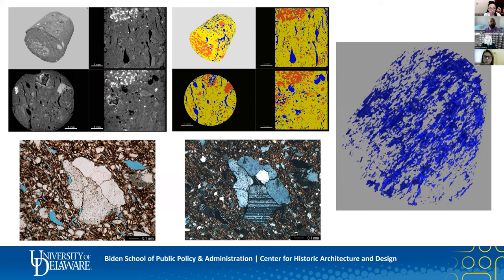For example, on the upper left is a micro-CT scan of a ceramic sample with a 0.5 centimeter field of view and 10 micron spatial resolution. We can see that there are a lot of silica mineral grains. They're unevenly distributed and they range widely in size and shape. With a bit of effort, the white denser quartz particles can be distinguished from other particles, but it's very difficult to separate out all of the other particle types from each other. It's a lot easier to just segment pores versus all silica particles versus ceramic matrix, as was done in the upper center image. I use the Dragonfly software by Object Research Systems for my 3D segmentation and image analysis.